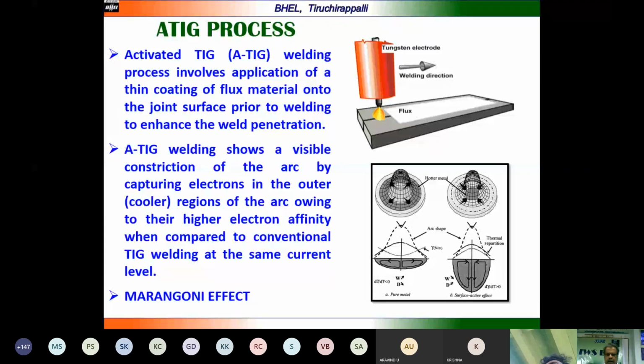You can see here, once you apply the flux, due to the Marangoni effect there will be a constriction of the arc like plasma arc welding, and the heat will go narrow and deep into the weld metal, and a deeper weld can be produced. So deeper penetration can be achieved by using this activated TIG welding process, and up to 12 mm thick stainless steels have been welded in a single pass. That is a claim in the literature. Up to 7 mm, carbon steels can be welded in a single pass.